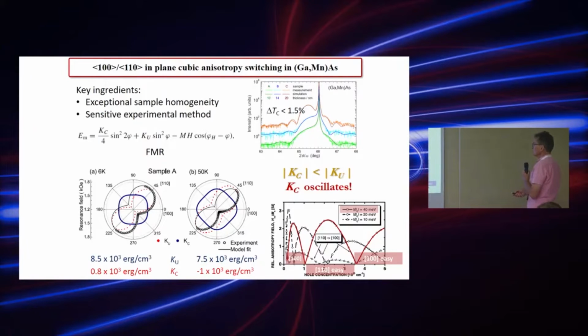So there is a clear 45-degree rotation between these two cubic components, and this actually means that the cubic anisotropy constant has changed sign. This 45 degree rotation means the change of sign. However, what is very important here, please note that the uniaxial anisotropy constant is an order of magnitude stronger than the cubic term.